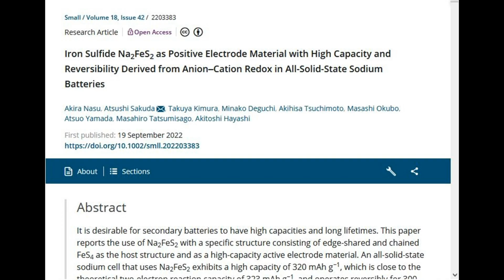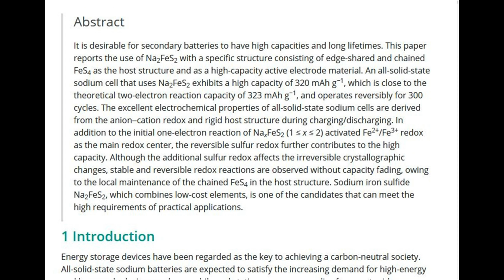Iron sulfide Na2FeS2 as positive electrode material with high capacity and reversibility derived from anion cation redox in all solid-state sodium batteries. Abstract. It is desirable for secondary batteries to have high capacities and long lifetimes. This paper reports the use of Na2FeS2 with a specific structure consisting of edge-shared and chained FeS4 as the host structure and as a high-capacity active electrode material. An all-solid-state sodium cell that uses Na2FeS2 exhibits a high capacity of 320 mAh/g, which is close to the theoretical 2-electron reaction capacity of 323 mAh/g, and operates reversibly for 300 cycles.